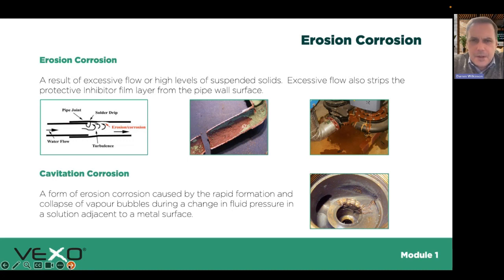Another form of corrosion is erosion corrosion. If the flow rates are too high, I know it sounds like you're asking for the Goldilocks zone here. They can't be too low, and they can't be too high. Got to be just right, like the Three Bears story. But you do have to have your flow rates right. If you do not, you'll encourage deposition, but at the same time, if you have too much, you could start looking at erosion corrosion as well, particularly on the softer metals. So the picture on the top left is some copper. You can see that scouring that's occurred.